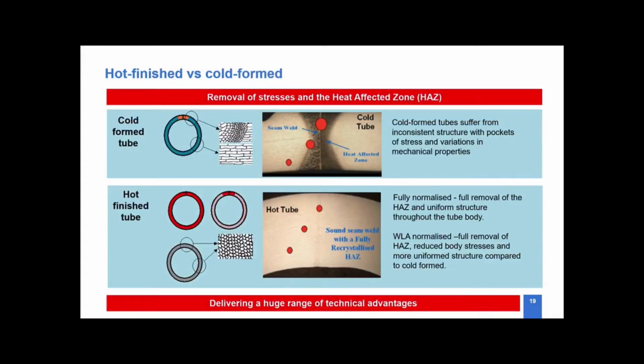The big difference to highlight when people don't specify the tube specifications correctly is this hot versus cold form. So the welded process route, everything starts off as a cold form tube. And you can see this heat affected zone. You can see the area where, if you cut through the tube, we have this sort of discoloration. This is because the microstructure in that area has changed. It's distorted. So it's very brittle.